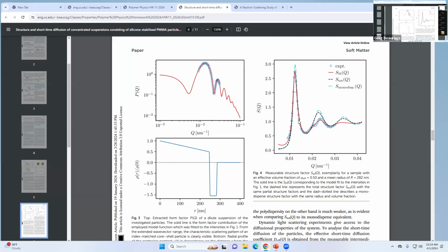In other words, you can't take this and draw a picture of what the thing is. It's like an average, a mean thing. So you're going to get mean information like density. Density's high at some distance, but it doesn't tell you what the actual crystal structure is. You can use a model and then analyze this and get the crystal structure, but it depends on the model. And you could use more than one model to get the same answer.